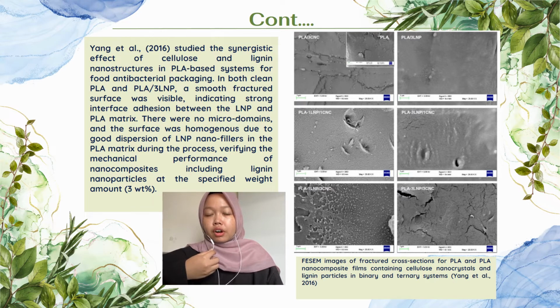FESEM micrographs of neat PLA and PLA nanocomposite fracture surface are shown in the picture. In both cases, a smooth fracture surface was visible, indicating strong interface adhesion between the LNP and PLA matrix. So there were no microdomains and the surface was homogeneous due to the good dispersion of LNP nanofillers in the PLA matrix during processing. Verifying the mechanical performance of nanocomposites, including lignin nanoparticles at the specified weight amounts.